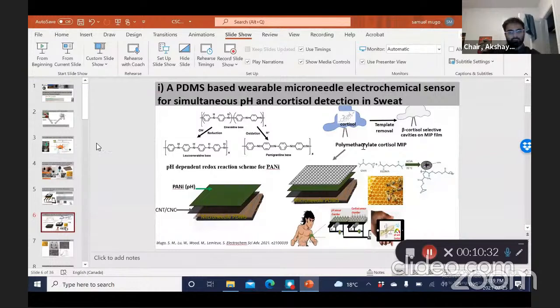And again, I've published this work, so you can check the details there, which is you take the glycidyl methacrylate cross-linked with ethylene glycol dimethacrylate, and using radical polymerization you create those cavities, and then you extract the template, which is cortisol in this case, and we do so using an electrochemical cleaning method.